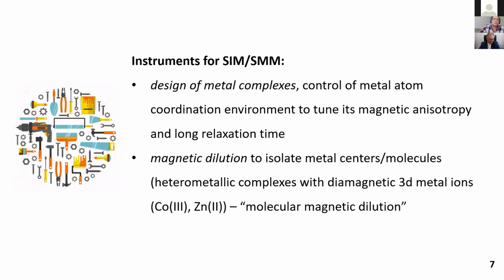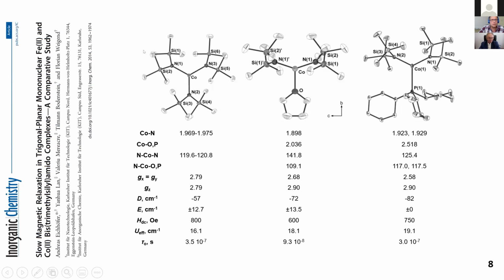And some works have information about controlling the magnetic characteristics of cobalt ions. For example, this work shows a triangular complex of cobalt with three bis(trimethylsilyl)amido ligands. One of them could be replaced by THF or triphenylphosphine, and all of them demonstrate slow magnetic relaxation in zero field. An increase in the electron-donating properties of the ligand from nitrogen to phosphorus, and a change in the geometry of the coordination environment of all these compounds, led to a decrease in D value and a certain increase in the magnetization reversal barrier.